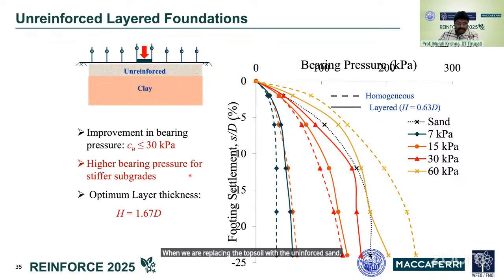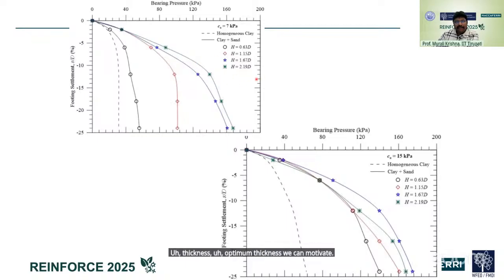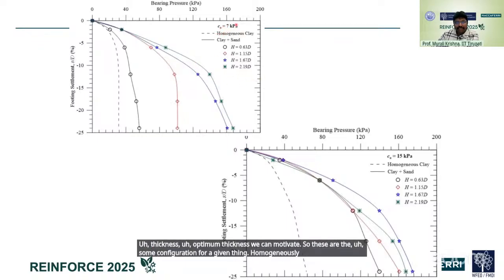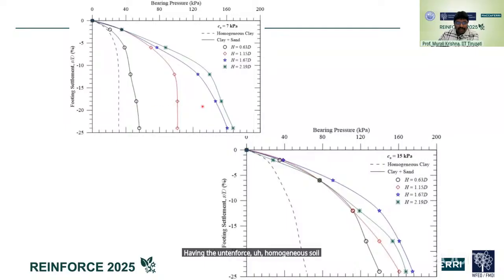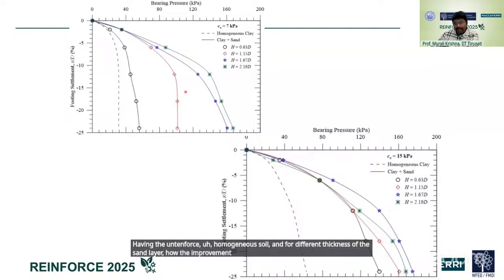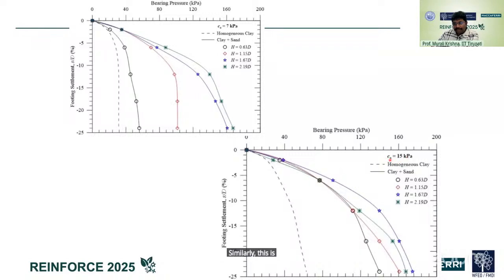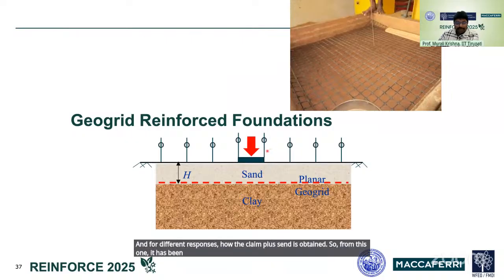While conducting the test for different layer thicknesses, the optimum layer thickness was obtained as 1.67 D. If you replace the top 1.67 D with sand, it's the optimum thickness. The thickness we can modify. So these are some configurations. Homogeneous clay with only 7 kilopascals soil is the unreinforced homogeneous case, and for different thicknesses of the sand layer, the improvement is represented here. Similarly, this is for the 15 kilopascals undrained shear strength soil, and for different responses, how the clay plus sand behaves. From this, it has been observed that 1.67 is ideal.